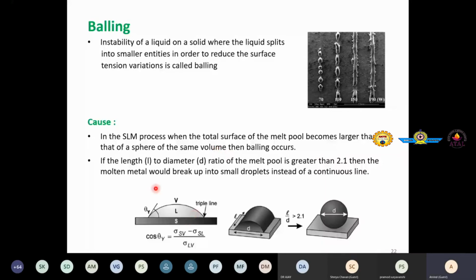For example, in the figure below, it is shown that if the length L to diameter D ratio of the melt pool is greater than 2.1, then molten metal would break up into small droplets to minimize the surface energy according to minimization of surface tension, and we will not get a continuous track. So here in this figure, you can see that if we use less laser power, right, we are expecting balling defect. As the laser power is increased, such phenomena is reduced. Same way, it can be related with other process parameters like scan speed, spot diameter, layer thickness, and everything, right? All are interrelated. So the takeaway message is that we need to minimize this balling defect because we want a continuous track.